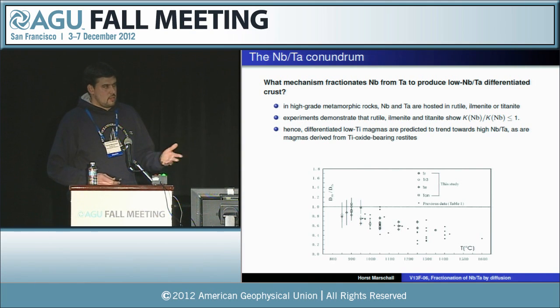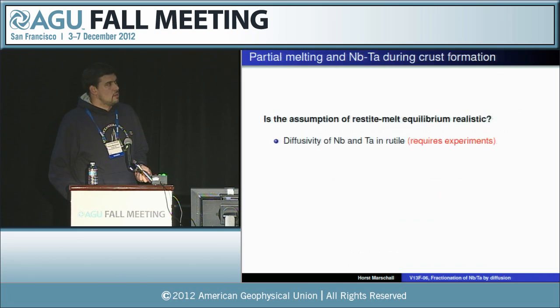So the consequence of that is this conundrum that the continental crust, which should represent the fractionated product of partial melting, has lower niobium tantalum ratios, whereas all the equilibrium melting models predict that it should have a very high niobium tantalum ratio. So all the equilibrium models have failed to explain that paradox. So that's why we went as far as to question the assumption of restite-melt equilibrium.